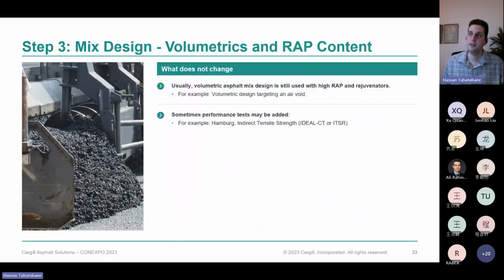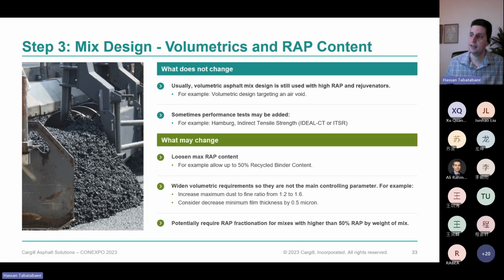Some changes sometimes are made on the mix design process when you're using a recycling agent with high RAP. The volumetric part might not change too much. There may be some performance tests like an indirect tensile strength or a wheel tracking test that might get added. However, a specification will require a loosening up on the maximum RAP content allowed.